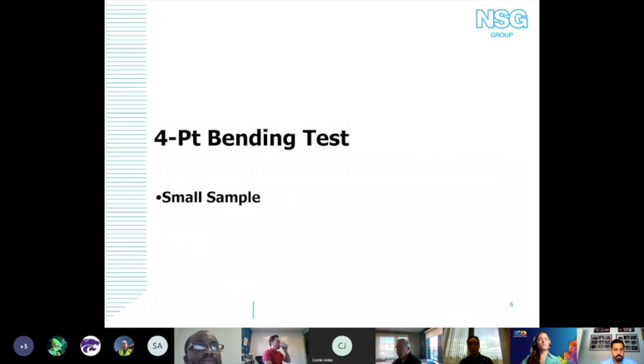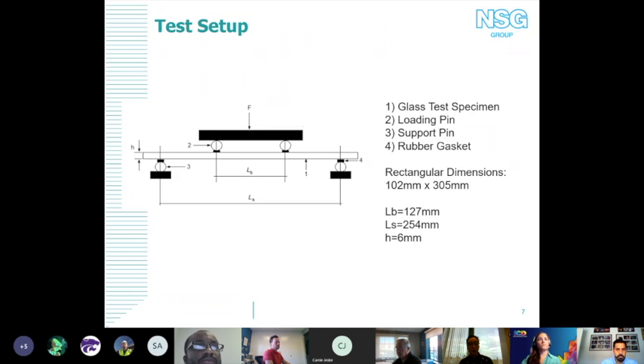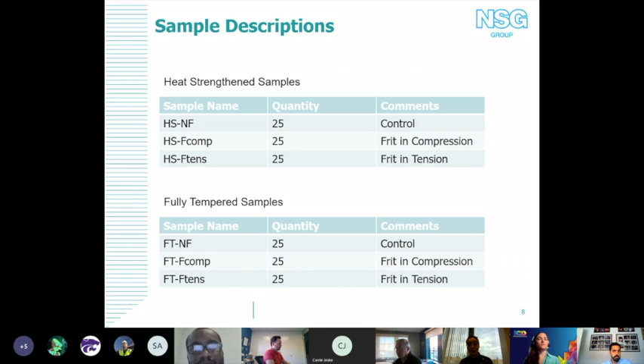Next slide. So we'll just start with the 4-point bend test. In these, they were really small samples, about yay big, handheld. But we did 4-point bend test. So essentially your maximum stress would be the entire area between your top 2 loading pins. So that way we knew it was always fracturing at a location of maximum stress. So we tested heat strengthened and fully tempered lites. In these, we had our uncoated controls, and we tested with the frit in tension and the frit in compression to see if there was any difference with regards to where the location of the frit was.